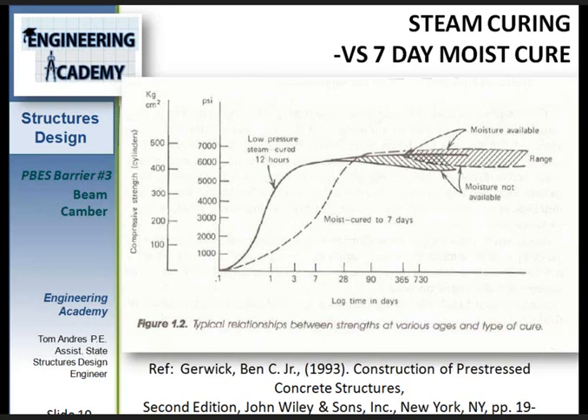And you can see the difference. The solid line on that graph is the low pressure steam cured for 12 hours versus your standard 7 day moist cure. So you can see the comparison.